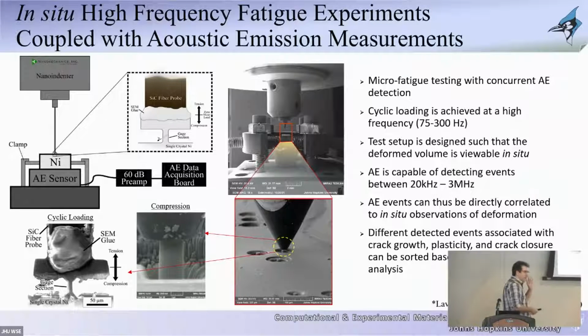The other one is SEM costs us $70 per hour. So if I want to reach millions of cycles, which is what happens for these materials when they fail, I need to do this fast because I don't have enough money to be able to pay $70 an hour for a few weeks. So we need to do this fast. So the way that we do it is using high frequency loading, which is an intriguing approach that existed for a while, but apparently no one has implemented it into the small scale world, which was quite unique when we published this work a couple of years ago. So this is basically the setup.